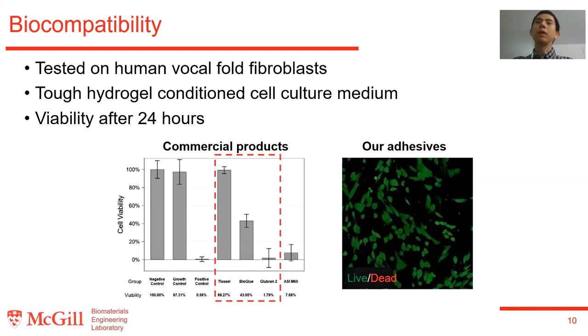When we look at the cytocompatibility data, our adhesive is biocompatible to human vocal fold fibroblasts, similar to Tisseel. I need to mention that we haven't finished the complete biocompatibility evaluation yet due to the COVID situation. The image shown here is the cytocompatibility of our adhesives before the freeze drying. However, we believe that the freeze drying procedure will not change the cytocompatibility of our adhesives. So we expect that our porous adhesive can provide a high biocompatibility similar to the result here.